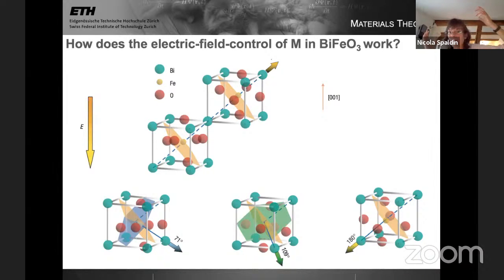There doesn't have to be any antiferromagnetic domain walls. Maybe there will be some just by chance, but there's no energetic reason for there to be an antiferromagnetic domain wall. But when I have a ferroelectric domain wall, say between this orientation of ferroelectric polarization and this one, then my easy plane of antiferromagnetism has changed. I don't know if you'd call it really an antiferromagnetic domain wall, but a discontinuity in the antiferromagnetism, because the plane in which the magnetic moments are oriented has changed. That's what's being picked up by the PEEM: the whole easy plane of antiferromagnetism has changed. I guess you would say the L vector changes with it.